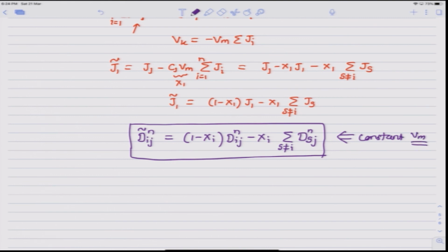So we can say this is the extension of Darken's equation to multi-component systems. This relation will be useful when we are trying to correlate our interdiffusion coefficients, which can be easily obtained, to intrinsic coefficients or to the fundamental atomic mobilities through thermodynamic factors. And this kind of relations we have seen before.